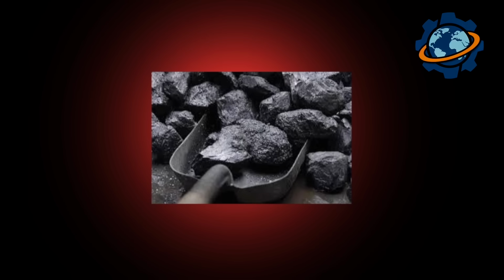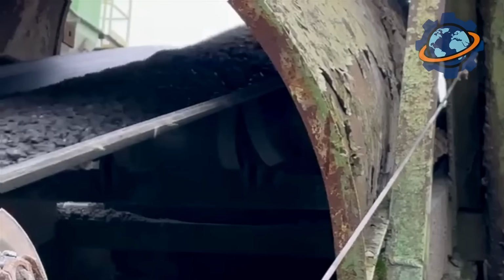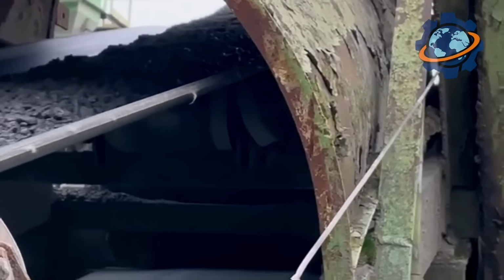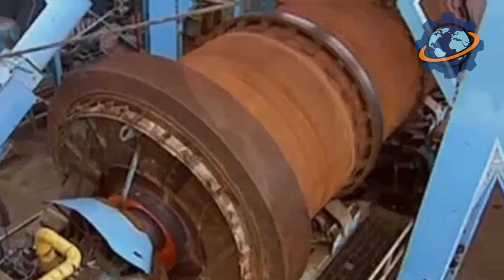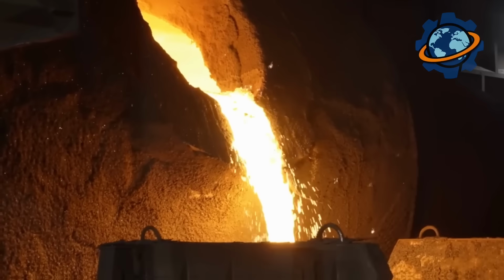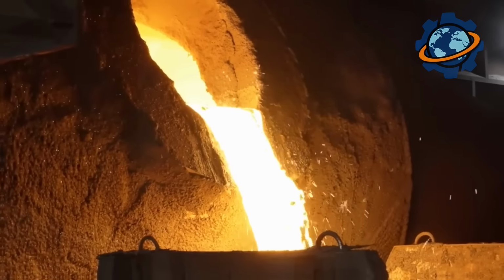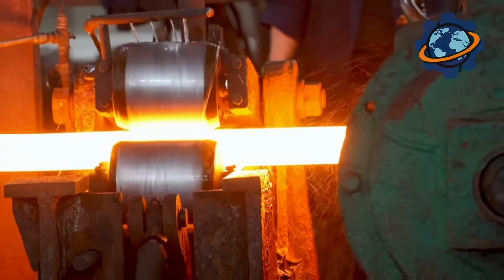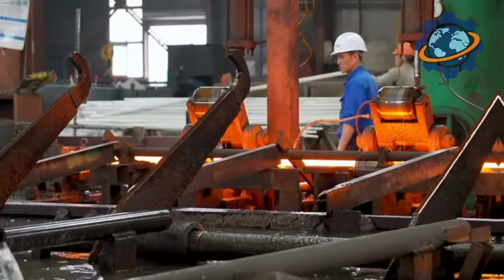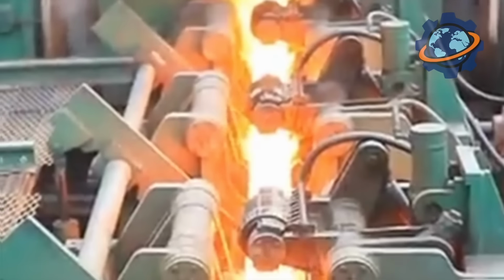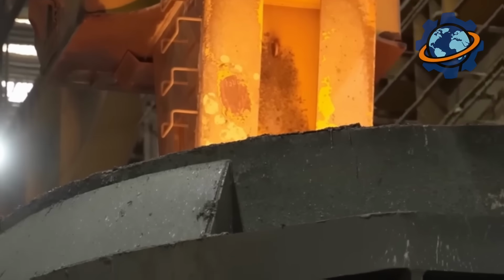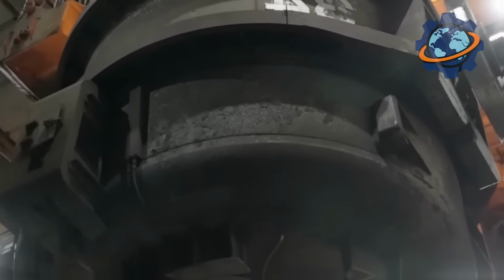And so, traveling from explosions in 2,000-foot-deep quarries through giant crushers and magnetic separators, through 300-foot-tall blast furnaces at 3,600 degrees and converters where oxygen burns out carbon in 20 minutes, through rolling mills where 8-inch slabs become millimeter-thin sheets, steel emerges, the metal that built civilization.